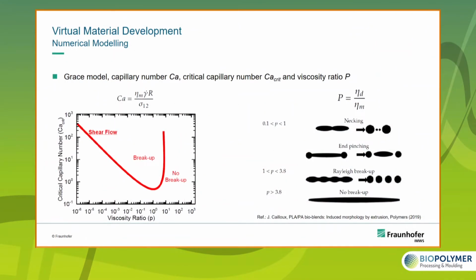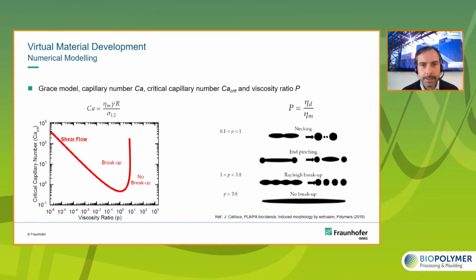So in here, you can see the Grace model and the capillary number, which is the key parameter in this model. The capillary number is the quotient between the viscosity of the matrix of your compound times the applied shear rate during processing, divided by the interfacial tension of your polymers. And whenever those two quotients meet each other, you have the so-called critical capillary number. This is the red line in the lower diagram on the left side. And whenever the capillary number is bigger than this critical capillary number, you will have particle breakup, meaning you have a refinement of your microstructure, of your morphology. And this again is depending on the viscosity ratio of the polymers you are using.